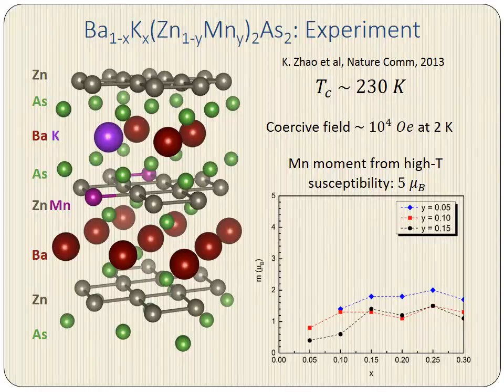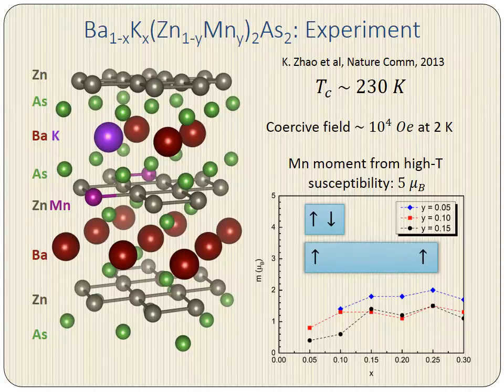There is a mystery, though. Direct magnetization measurements indicate a sharp reduction in the local moment. Here we see that for all doping levels, the magnetization per manganese does not exceed 2 Bohr magnetons. Now, the authors speculated that this could be due to the formation of antiferromagnetic singlets that compete against a longer-range ferromagnetic ordering, although no exact mechanism was specified. The magnetization per manganese also exhibits a curious doping dependence, which eluded explanation in the original paper. Here we note that with increasing hole doping, the magnetization generally increases. A successful theory should be able to account for this dependence and overall reduction.